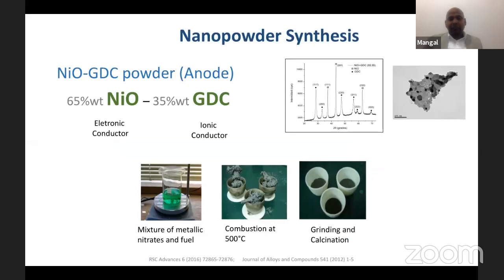So as I mentioned, from the starting powder, there are many methods available, but we have to adopt simple methods. In our case, we started to synthesize using a rapid synthesis process called combustion synthesis. Also, we have adapted the precipitation technique. But even in this, you have to think about the powder characteristics. Normally, when you want good fabrication materials, you need spherical particles. But with precipitation and other advanced chemical methods, it is easy to fabricate spherical kinds of powders. Also, you can modify the surface of